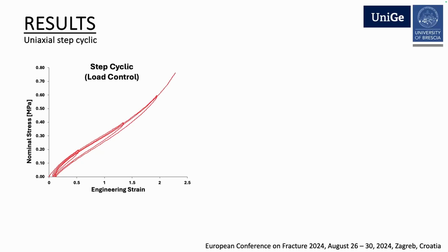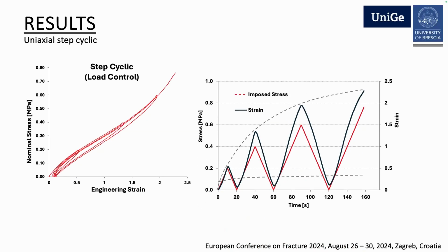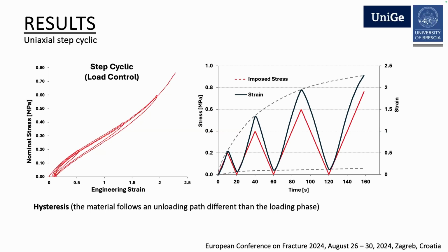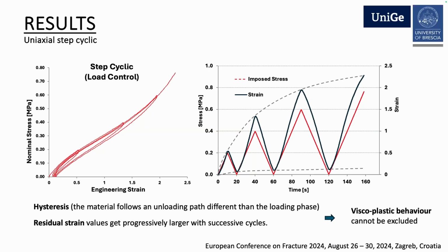Considering the uniaxial step cycle test in which the load is increased in the different phases, so the material is loaded and then unloaded, again we observe the presence of hysteresis and of residual strain, which reasonably gets larger as the load level increases. And if we consider this indication from a modeling point of view, this seems to suggest that some irreversible deformation is probably present. So viscous response should be combined with something like, for example, a plastic behavior.